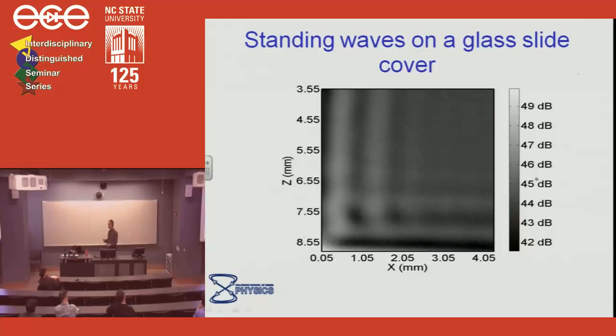Do you understand the geometry? So here's my glass slide, which is probably only 100 microns or 50 microns thick, and we're scanning on both sides, and the transmitter tip is actually setting up these standing waves on the glass slide. And we have enough dynamic range that we can see that without really any difficulty.